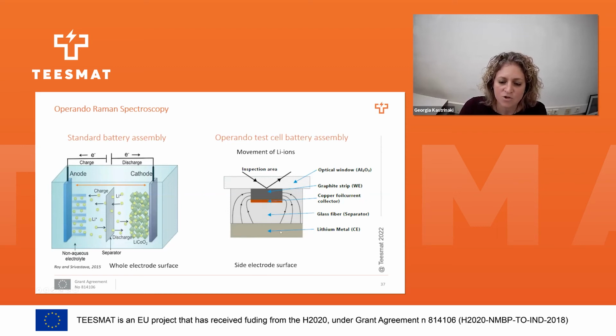So what happens is that the lithium ions do not follow this route, but the working electrode is actually receiving the lithium ions from the side. So it's a different kind of inspection. If this is a graphite strip, during intercalation, when you are charging, you have the lithium ions coming from the outer part to the inner part, and then during discharging they move back again from the outer part.